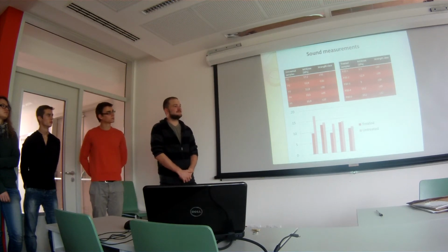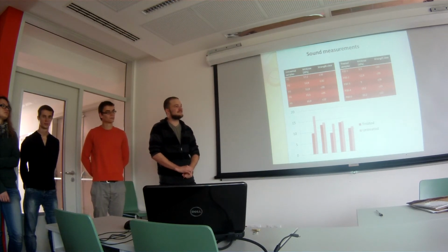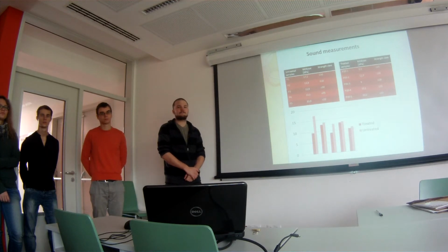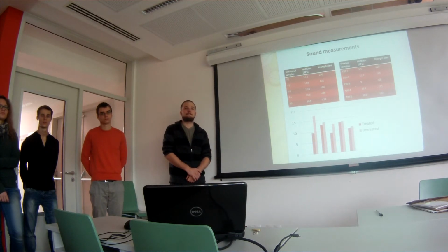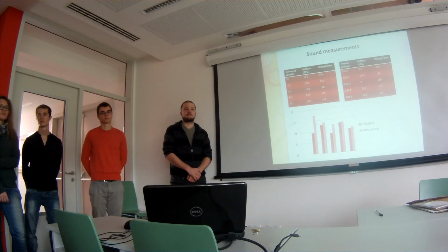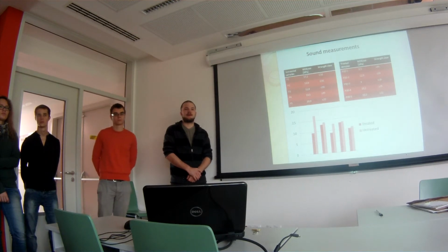C50 is kind of nice. It's not your fault, but those data are done on regular, untreated wood, with lots of sample specimens, and there is good statistics behind it. But I think you can use those data only for the same type of wood, which is untreated spruce, pine, whatever.